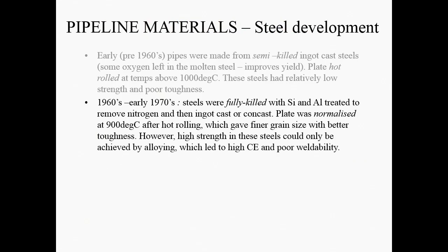So by the 1960s, the quality of steel was recognised as being not good enough because of all of these things left in the steel. And steels were fully killed. So in order to get rid of the oxygen in the steel, rather than relying on the manganese, which had been originally used in the steel-making process, small amounts of silicon and aluminium were added. And they remove both any excess oxygen, and then they remove nitrogen that might be dissolved in the system.